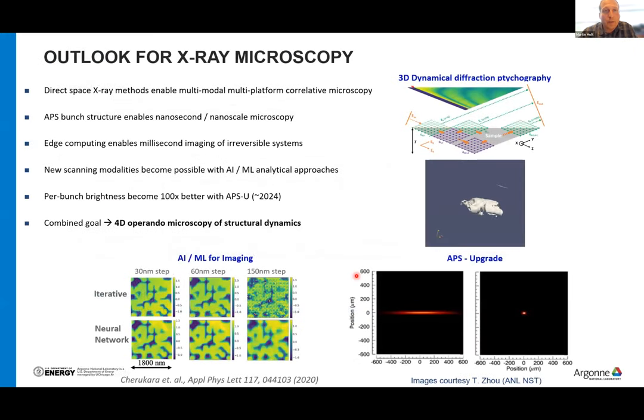Okay, so looking to the future, obviously the upgrade is at the diffraction limit, which is literally the best thing you can do for microscopy. And we're attempting to bridge this into three dimensions. This recent work by Tao Zhou is able to distribute the dynamical diffraction by solving Takagi-Taupin equations in a graph format that allows it to directly use automatic differentiation. This is a relatively inexpensive way to recreate a three-dimensional volume that's dynamically diffracting. Synthetic data looks relatively good.